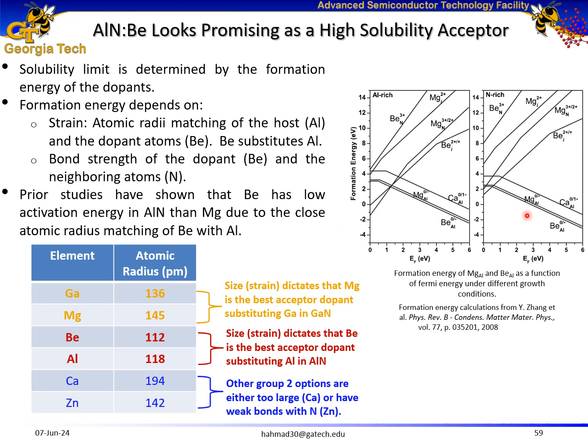The solubility limit of a dopant is determined by the formation energy of the dopant. Formation energy further depends on the atomic radii matching and the bond strength of the host versus dopant atoms. We know that in the case of gallium nitride, magnesium closely matches in terms of atomic radius with the radius of gallium in gallium nitride, so it is found to be the best p-type dopant in gallium nitride. By similar hypothesis, beryllium closely matches the atomic radius of aluminum in aluminum nitride and is potentially the best candidate as a p-type dopant in aluminum nitride.